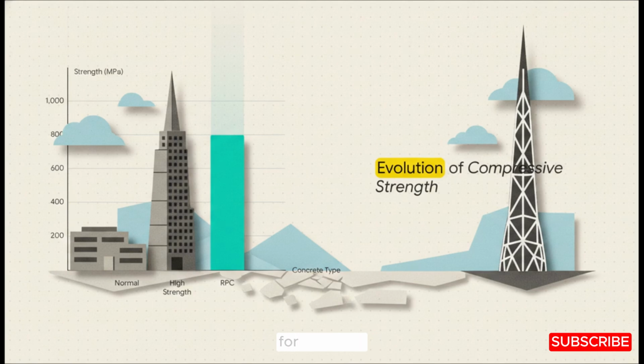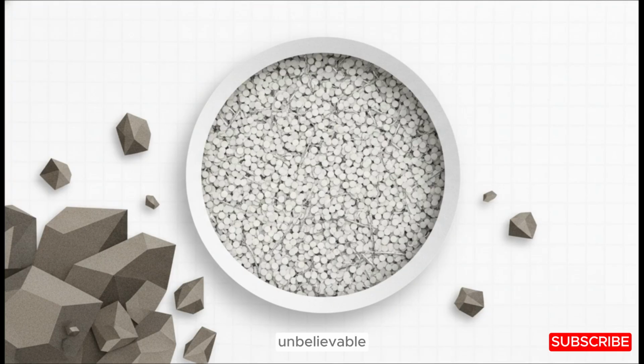Just to put that into perspective for a second, that is concrete performing with the strength of some actual structural steels. It's wild. Now, to achieve that unbelievable 800 megapascal strength, engineers had to completely rethink the recipe. Notice what's missing from the reactive powder concrete mix. There's absolutely no coarse aggregate, no rocks whatsoever. It replaces them with extremely fine-ground quartz measuring just 4 microns, fine sand, massive amounts of that silica fume we talked about, and microscopic steel fibers. By eliminating the larger rocks, they essentially removed the weak points where microcracks usually form, creating a hyperdense, highly ductile composite.